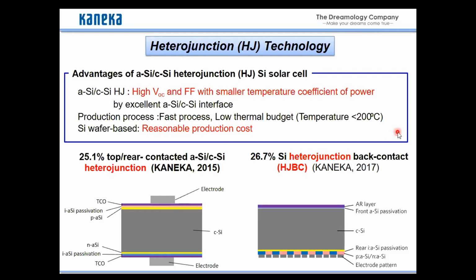Heterojunction solar cells are divided into two types by electrode design. One is what we call top and rear contact. Crystalline silicon is sandwiched by amorphous silicon and TCO, transparent conductive oxide. Then the top and rear contacts are, literally, a metal grid electrode put on both sides on the TCO. At the beginning, we started to develop this type of heterojunction technology and could achieve a record efficiency of 25.1% in 2015.